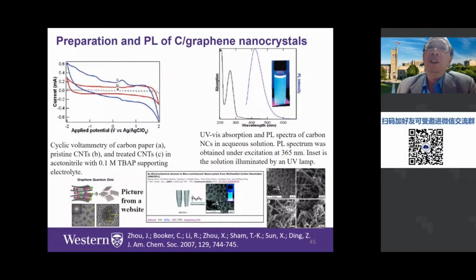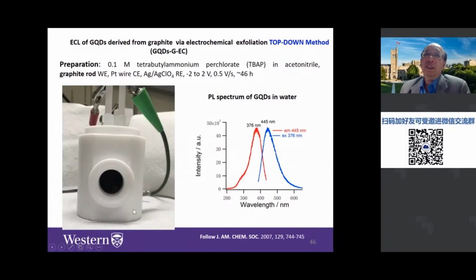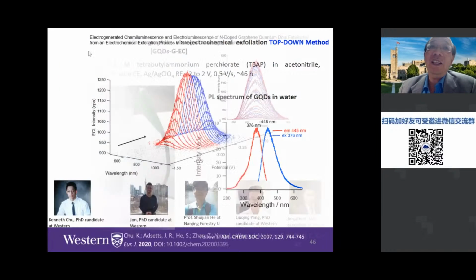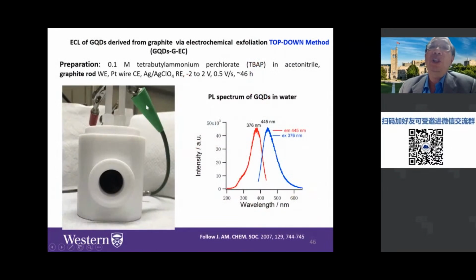So that's kind of the previous work. And then this time, we just use graphite electrode, and then we do the same thing. And fortunately we get the same graphene quantum dots, but with much lower cost, because multiple carbon nanotubes we still need to prepare, and it's expensive, while this graphite is much cheaper. So we just get these graphene quantum dots by what we call top-down method. That means we do the electrochemical exfoliation.